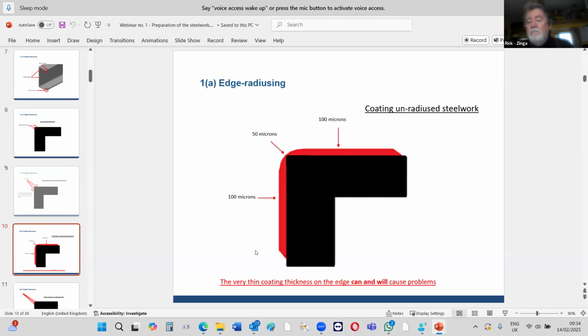So you might have an area that's slightly smoother along the edge of the beam, which you don't want. So you can see here what happens. The coatings pull back, and it's roughly 50 to 60 microns maximum you'll get on a sharp edge. And that area on a coating will break down very quickly from UV. In the case of Zinga, if there are any other influences around, any adjacent metals, that thin area can deplete quicker than the rest. So the 100 microns might give you a good 30 years, depending on where you are, but the edge, you probably only get 15, 20 years, and then you're going to have to redo it.